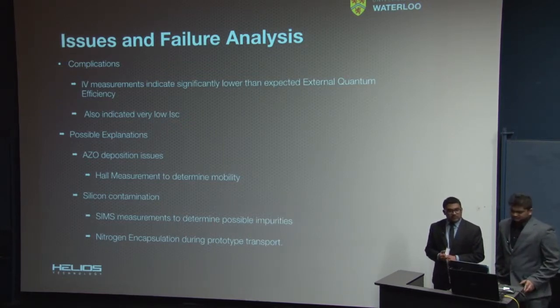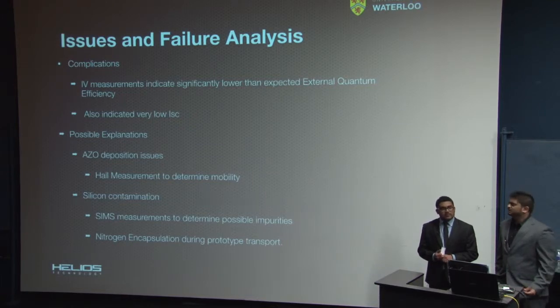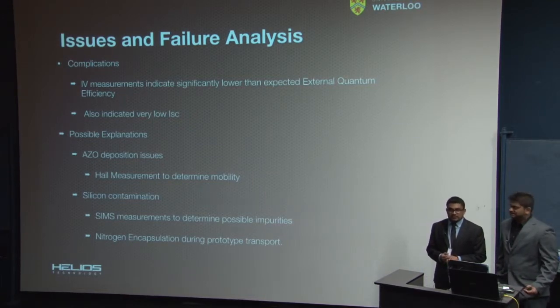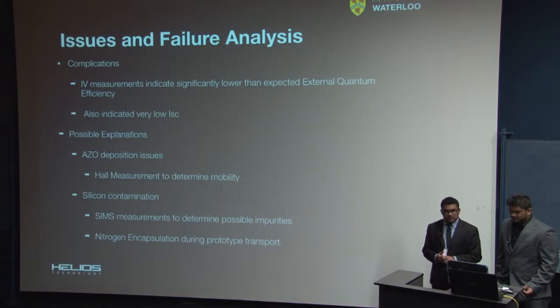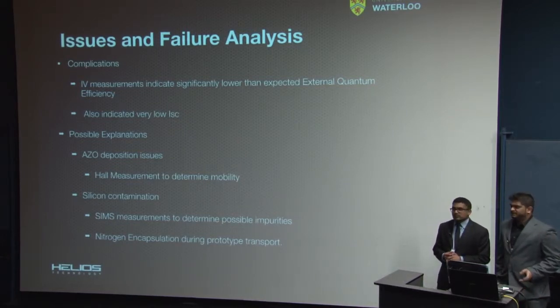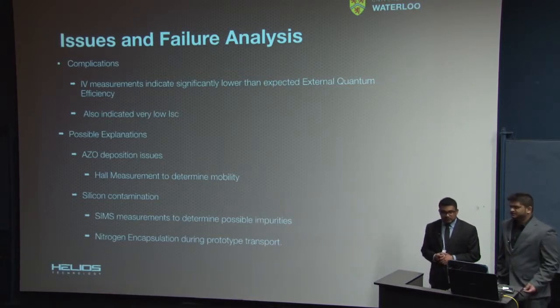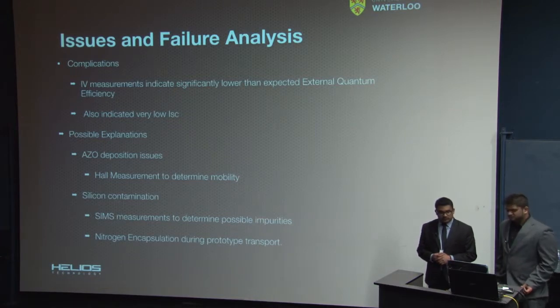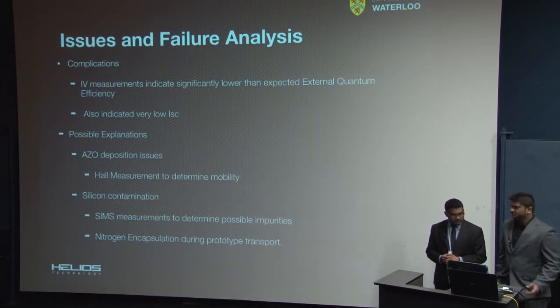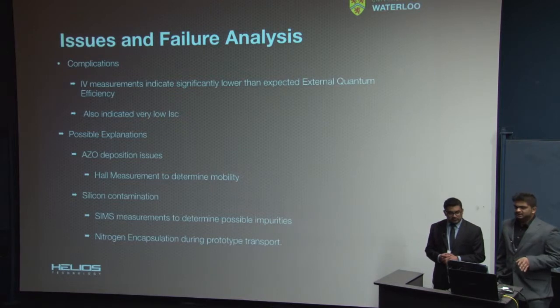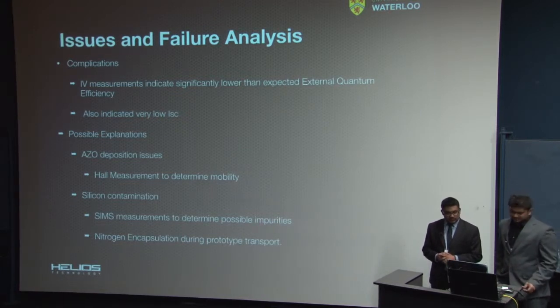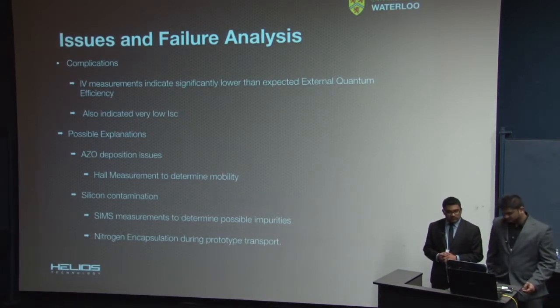As for possible explanations for this, we think that the biggest issue was the AZO deposition process with the sputtering. This process was not very even, and we think that's why the sheet resistance of the AZO is much higher than what we expected it to be. To continue with this, we plan to do a Hall measurement to determine the mobility of the AZO sheet, and this will allow us to continue further.